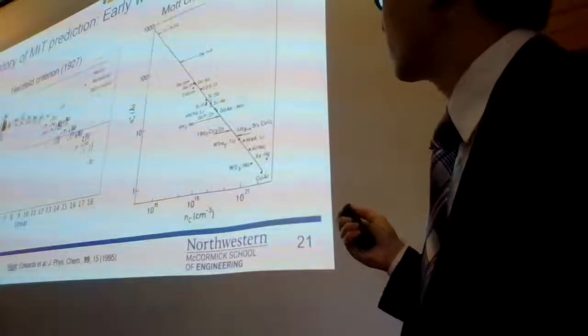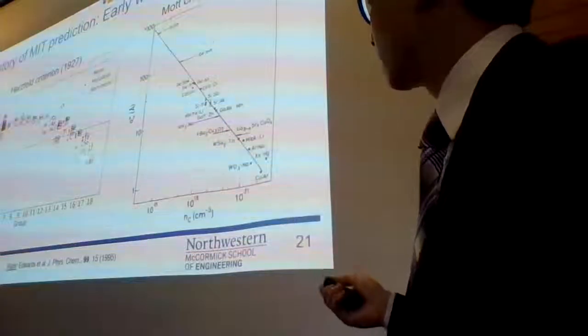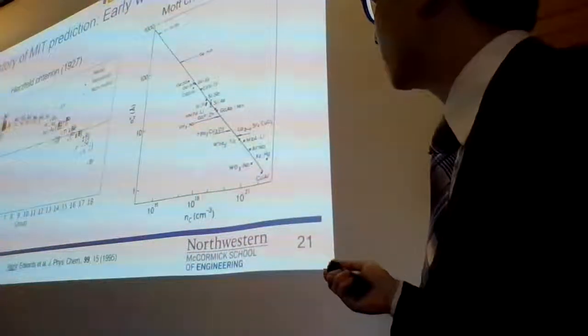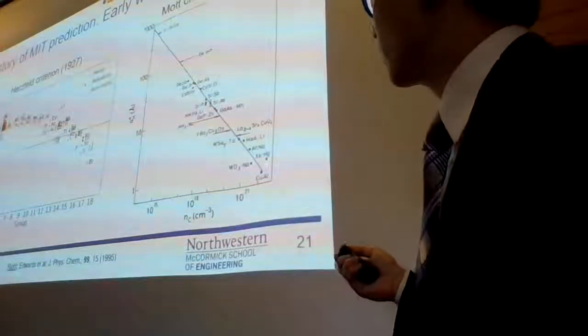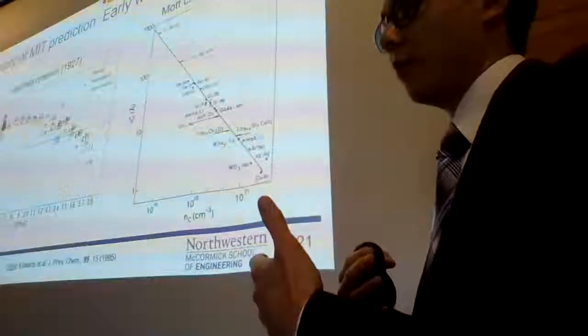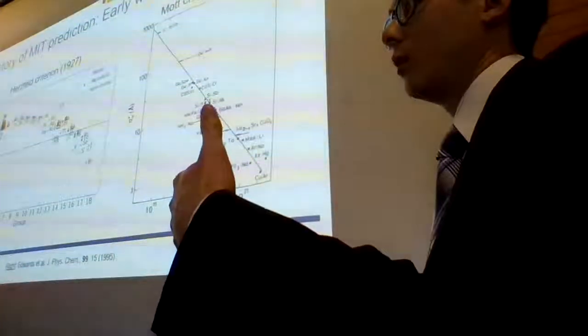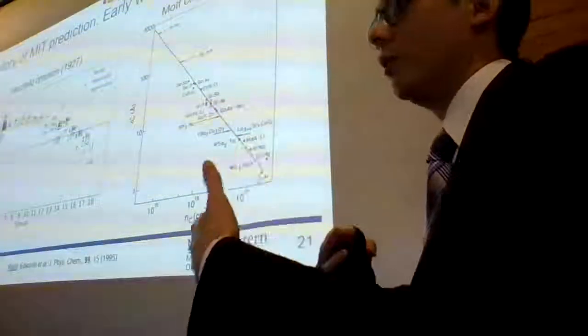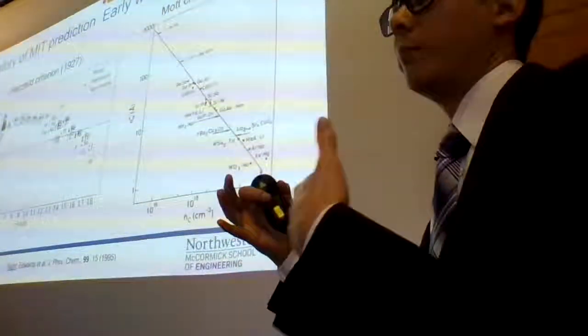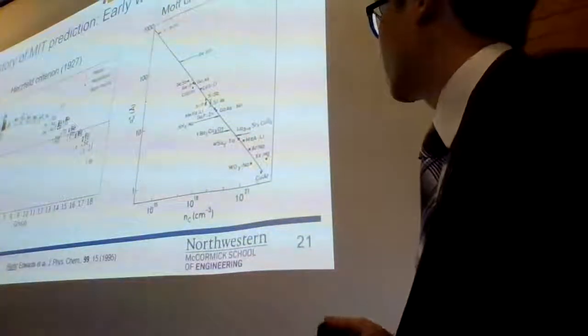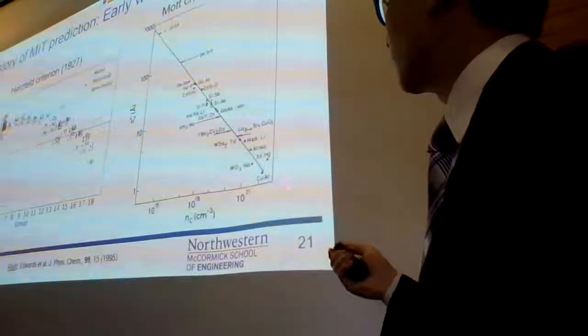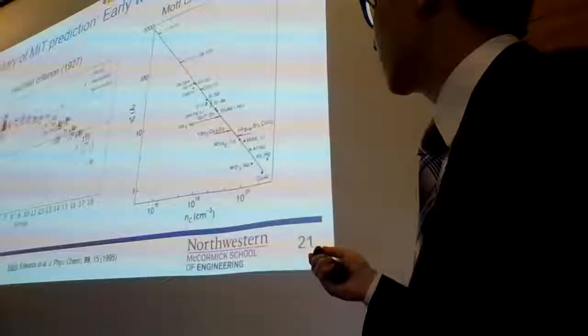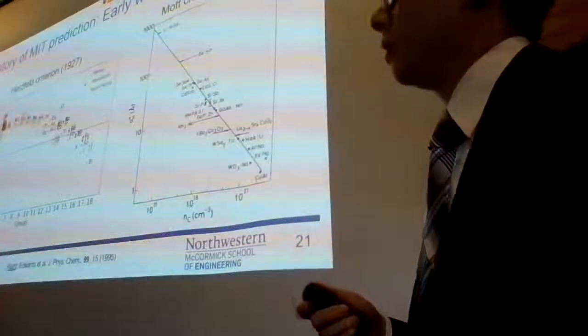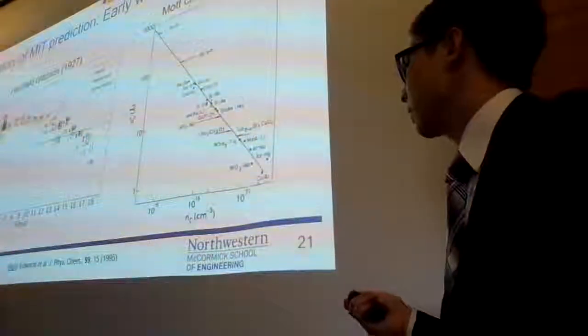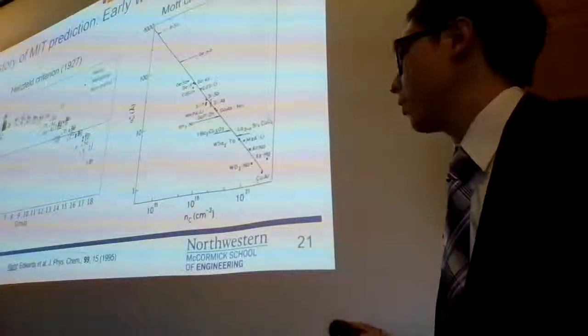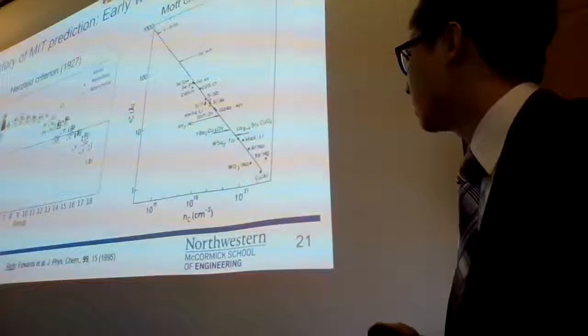Another effort earlier in the 20th century was the Mott criterion. This relates a critical density of carriers in the material to an effective Bohr radius. Essentially, the argument is that below a certain carrier density, the electrons will fail to screen electron-hole interactions in a material, and eventually they'll become bonded to each other and be unable to move. This theory actually describes a number of known metal-insulator transitions, including, say, a superconductivity transition in yttrium barium copper oxide. But the downside is that getting the critical carrier density often involves doing a number of experiments in the first place, getting a high-quality sample and things of that nature. So it's not very good for prediction.